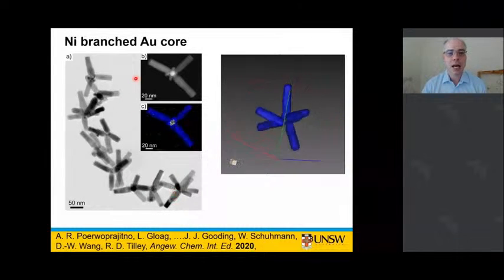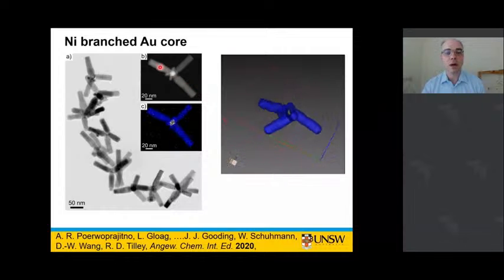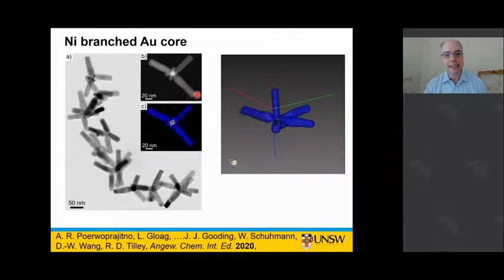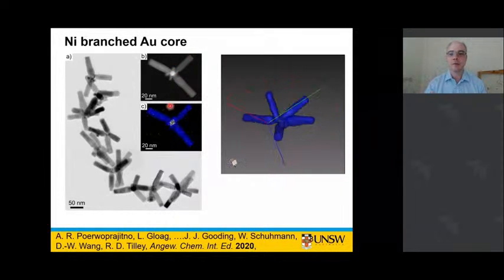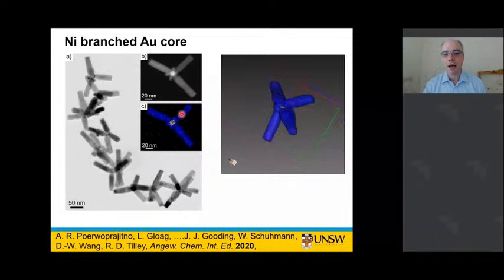And if we have a look at our dark field image and our EDS mapping, we can see that we can pick out the gold seeds, the gold cores, and then we're getting these nice nickel branches growing off our gold cores. And again, you can see we're getting the sharp facets that we're after, these low index facets that we're after for our catalysis.